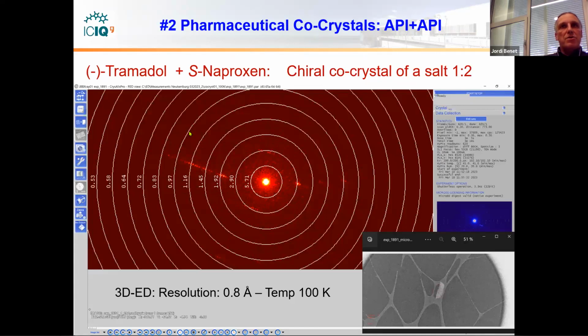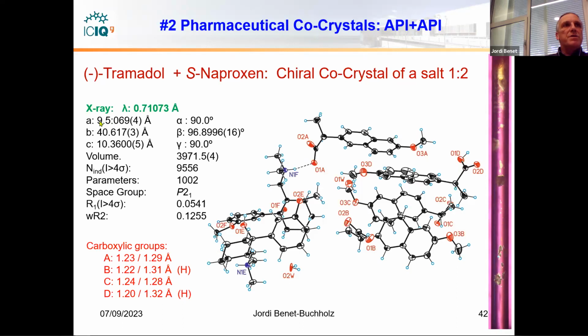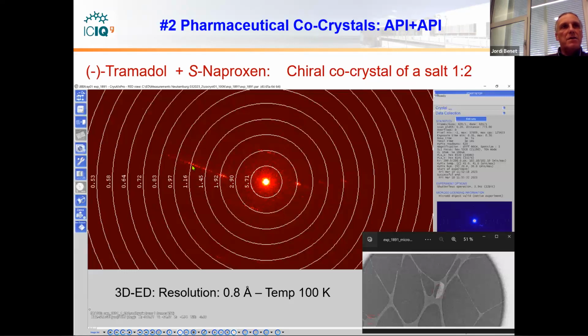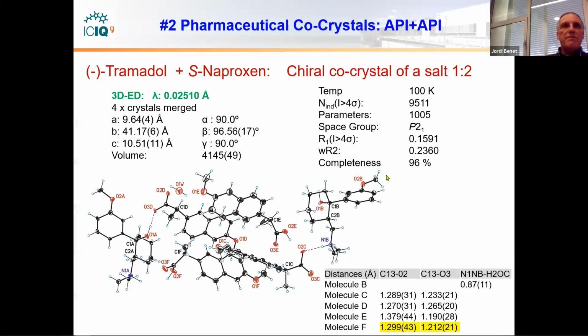As you can see, going back to here, we have a cell of about 9.5, 40, and 10 angstroms, and you can recognize quite nicely the long axis, which shows these closely appearing reflections. After measuring this sample, we measured a data set of 4 crystals, and we could get a suitable data set with distances which corresponded to the expected distances for these atoms and hydrogen bonds. And one important point, which will follow later, apart from getting the structure quite easily using cryopreparation and the 3D-ED system, is one point which I will explain later, related to the absolute structure of this molecule.